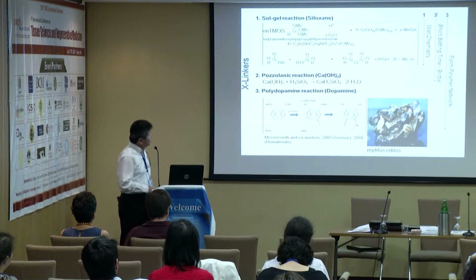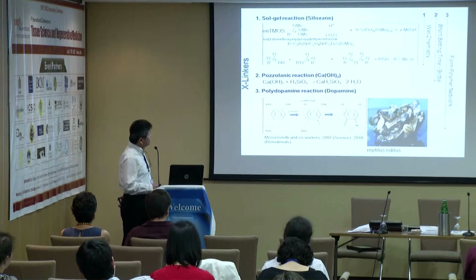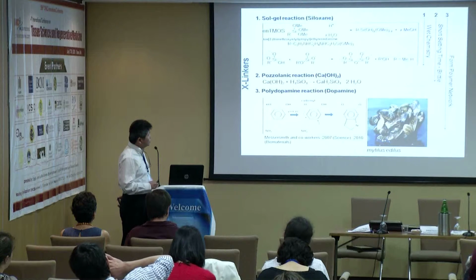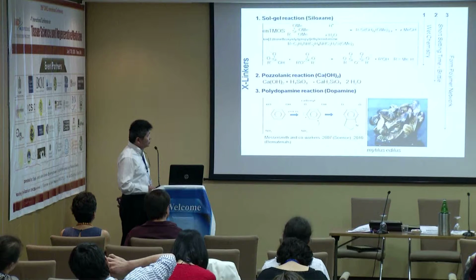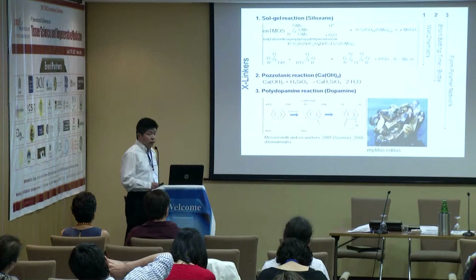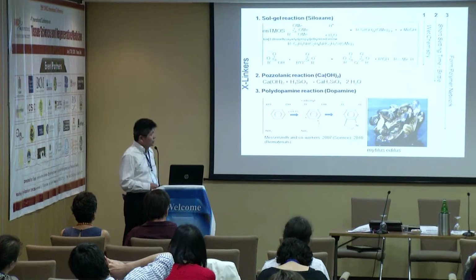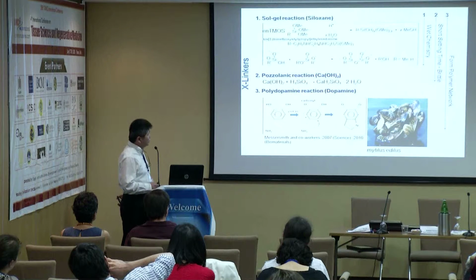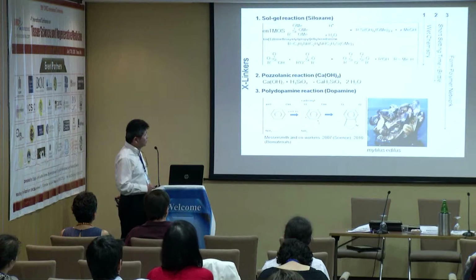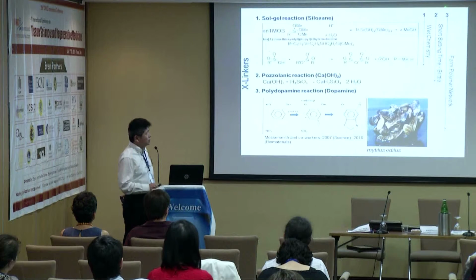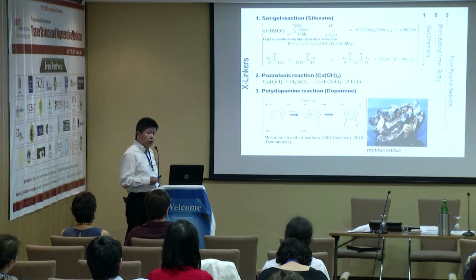So in the past, we have been developing several different cross-linking agents, and the first one is sol-gel reactions, which allow us to create a wet chemistry reaction. However, the reaction is a little bit slow, so it's not very practical. So we add another reaction, a pozzolanic reaction, adding calcium hydroxide into the system, which shortens the setting time and makes the material more resistant to wet conditions.